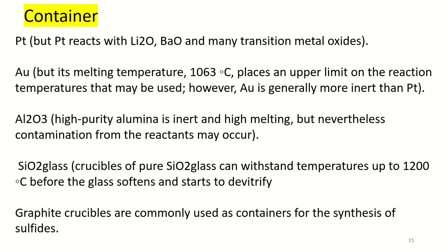So if we are using alkali metal oxides, the silicon dioxide glass should be ruled out, because of its reactivity towards alkali metal oxides.